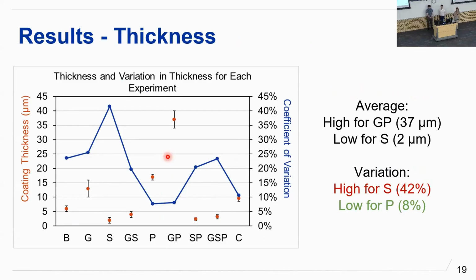So we were also interested in the thickness of the coating. In the graph on the right, or left for you guys, the overall thickness with the standard deviation is represented by the orange dots, and the coefficient of variation is represented by the blue lines. We found that the coating with the highest thickness was for high gas flow rate and high passes, and the coating with the lowest thickness was for high stage speed. And the highest variation, which is what we don't want, was for stage speed, and it was lowest for the high number of deposition passes.